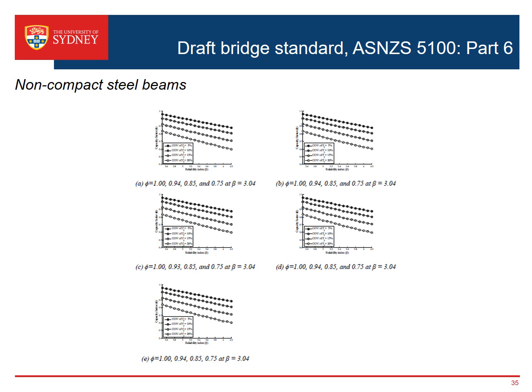But if we kept those other 2 limits constant, coefficient of variation of yield strength and reliability index, what we found is that the existing capacity factor is 0.9 for steel, and that was calibrated to all the steel that was used in the existing Australian standard. We found that from all the delivery locations around the world, we would be able to maintain a capacity factor of at least 0.94. So in that case, there was no cause for alarm, even though there may be some parts of the industry that thought there was.